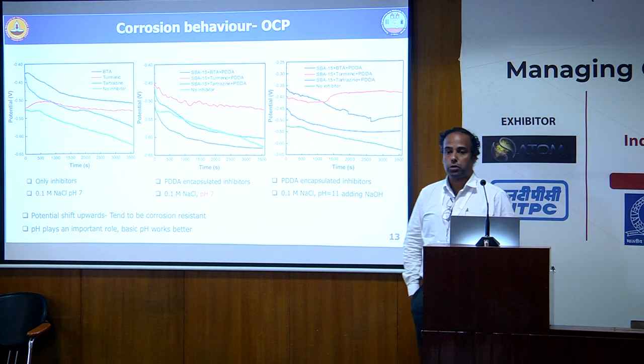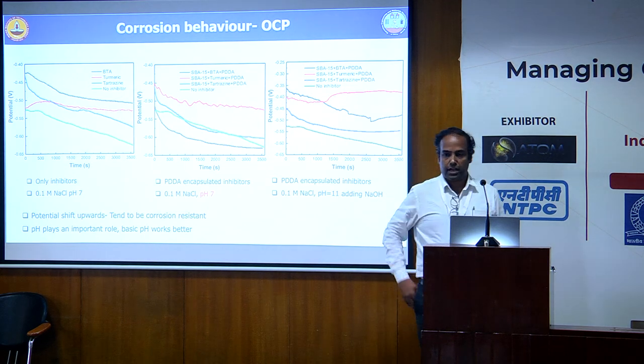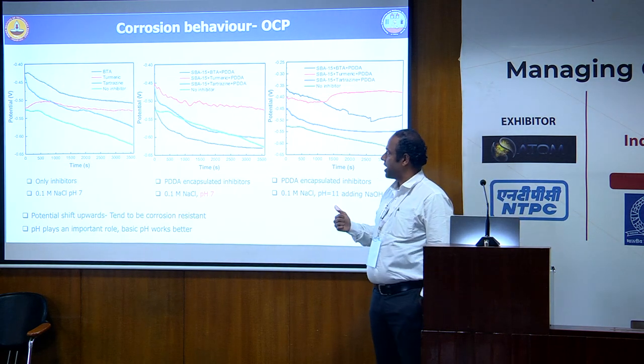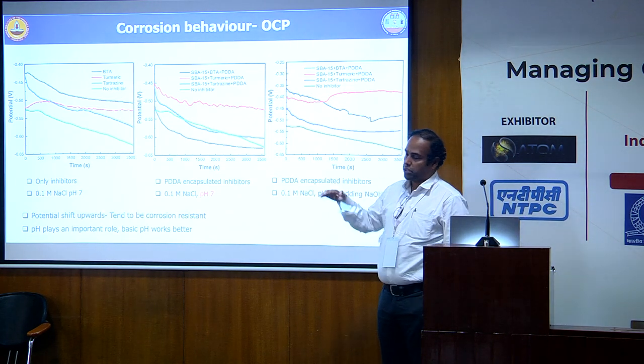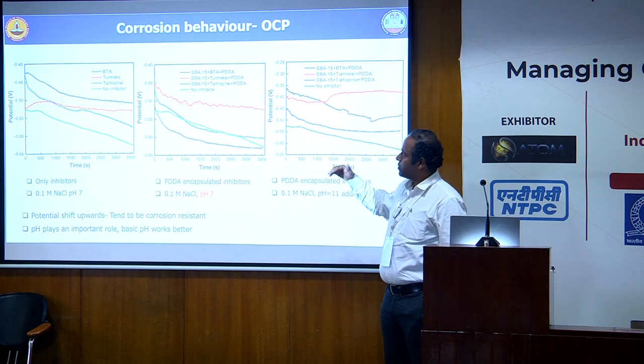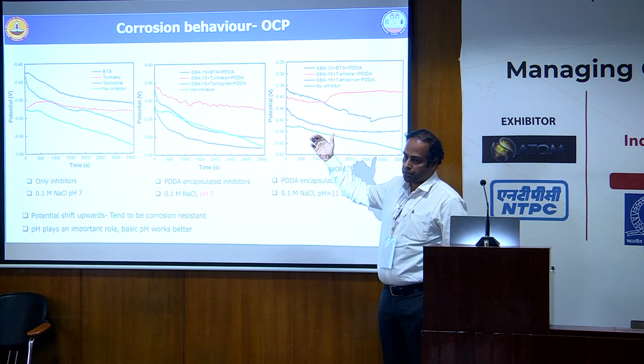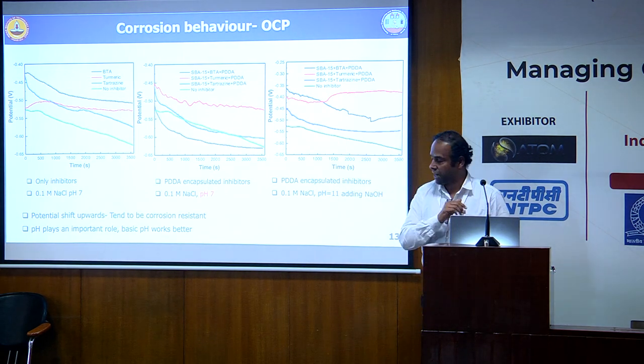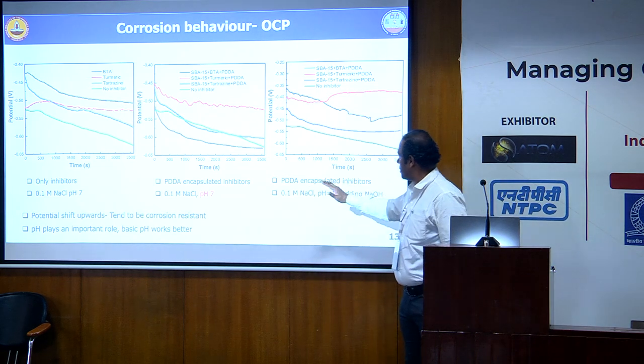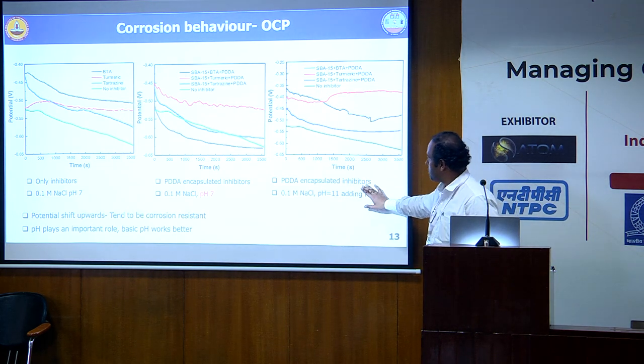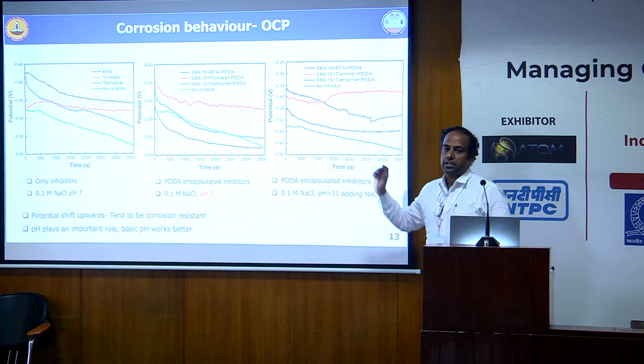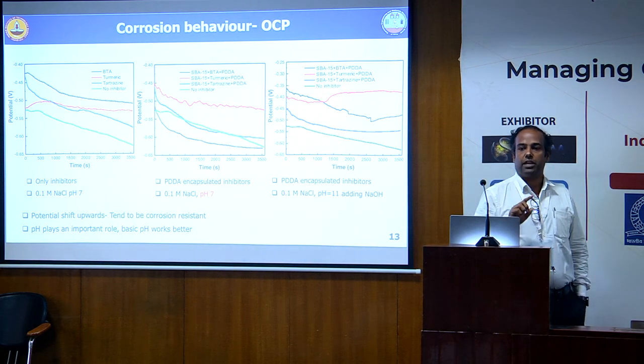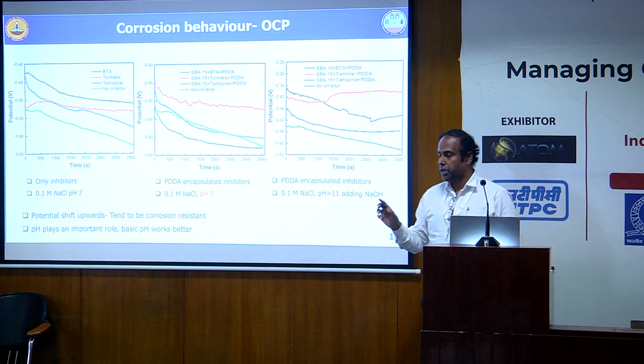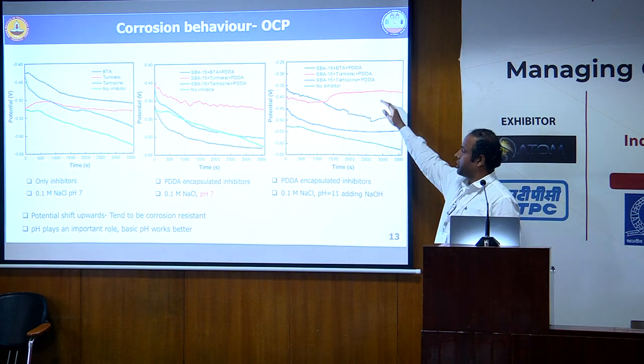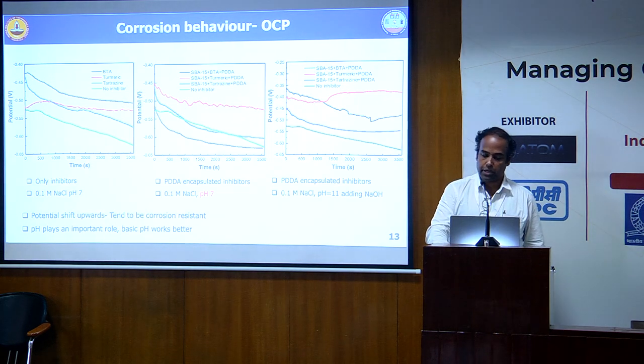And we checked for the corrosion behavior. We identified that, number one, the left image is one where we can easily say no inhibitor, the potential is more active. As you add inhibitors, you see the potential shifts nobler, which suggests that there is an inhibition action. And as we look towards pH 11, we also see a similar effect. That means even when I encapsulate the system, putting the inhibitor into it, it still acts. There is a shift in the potentials to a nobler direction.